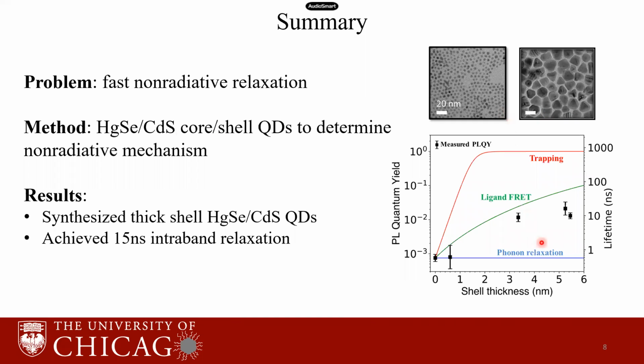And by measuring the quantum yield as a function of thickness, we were able to see a dramatic increase in the non-radiative lifetime. To tie this result back to my original motivation, this work shows the importance of engineering the surface of the quantum dot to obtain a slow non-radiative decay. So this tells us that for us to get efficient mid-infrared detectors, it is necessary to overcome this ligand FRET relaxation, either by growing a shell or by modifying the ligands on the surface.